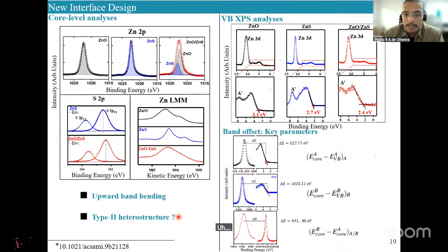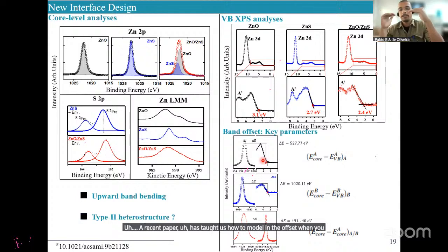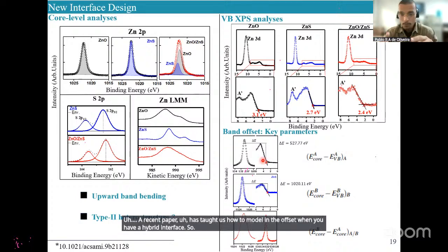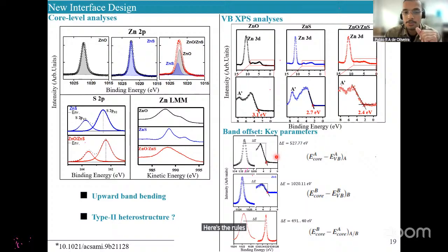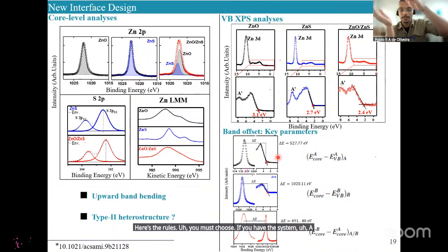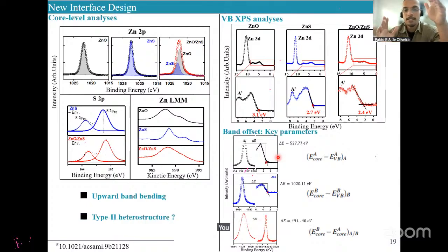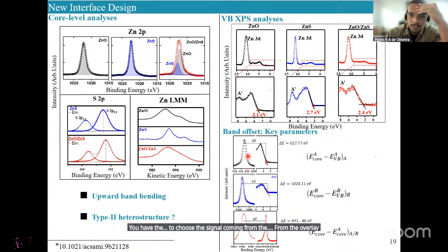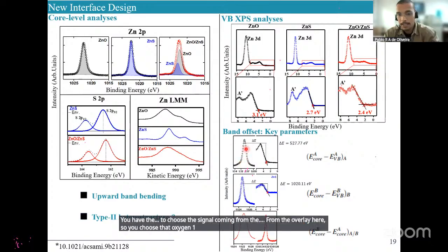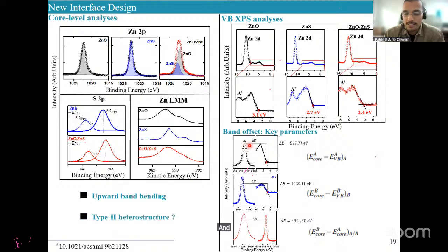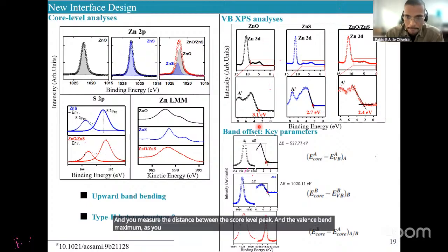A recent paper has taught us how to model the offset when you have a hybrid interface. So here are the rules. If you have system A, the overlay, over substrate B, you have to choose the signal coming from the overlay. So you choose the oxygen 1s as the peak, and you measure the distance between the core level peak and the valence band maximum as you computed before.